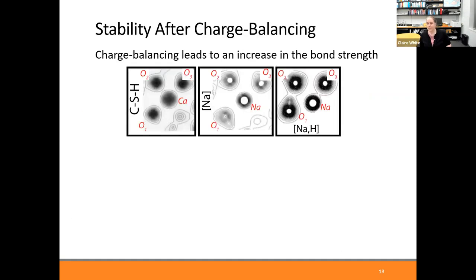So we can look at things such as bond strength, the impact of having the hydrogen in the system on the bond strength. And so if you look here, this is the baseline CSH. What we're looking at is electron density contour plots between different atoms. And specifically here, we're looking at between an interlayer calcium and surrounding oxygen atoms. If that calcium is replaced by sodium, you see that the electron density contour plots, there's less of them, the contours, there's less of them.